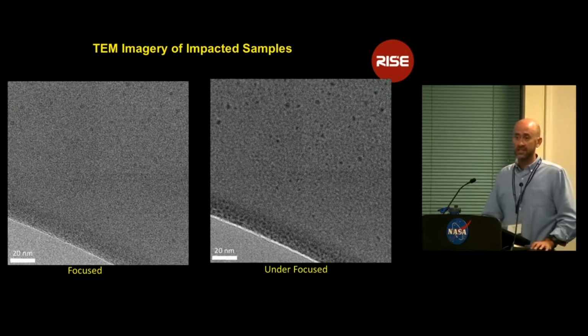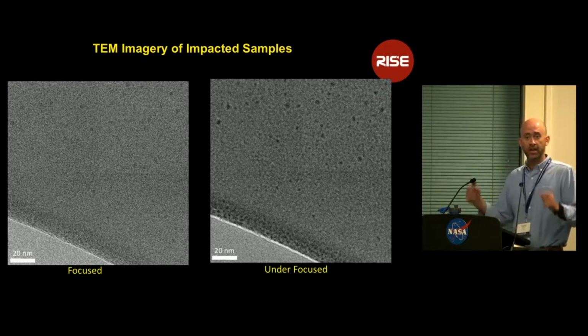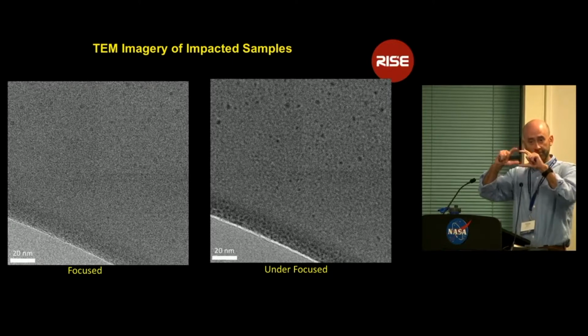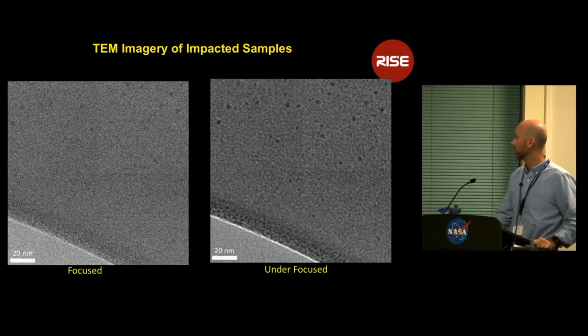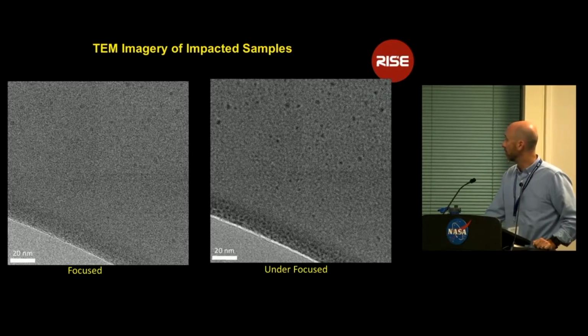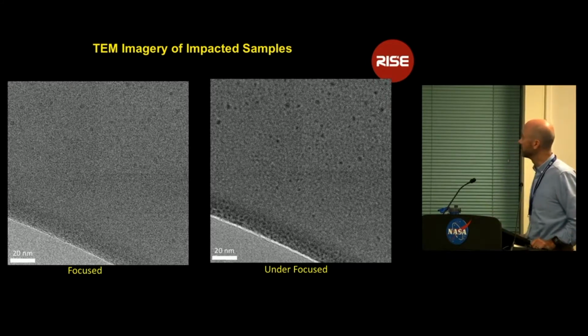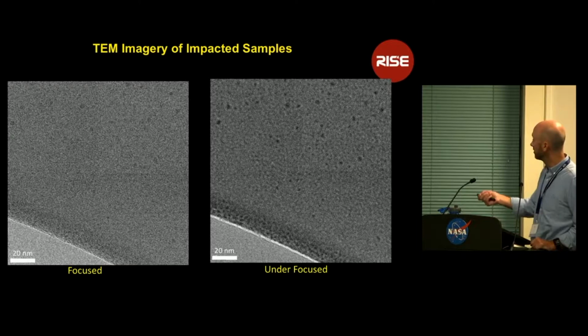Here are the first TEM data we got of these samples. So we got a FIB section sliced through one of the craters. Some colleagues of ours at Stony Brook were kind enough to collect these data for us at the Center for Functional Nanomaterials at Brookhaven National Lab. The underfocused image shows this best, where we see this kind of rim that's maybe 20 or 30 nanometers thick of darker material with smaller, 3 to 5 nanometer sized blebs here.